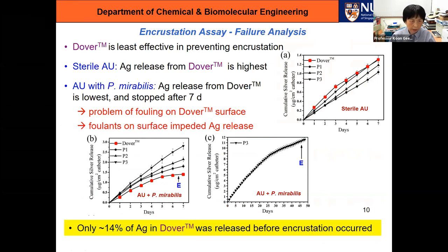So what went wrong with the Dover? This is a commercial catheter. So why is it not effective? Is it because it has limited amount of silver compared to our coating? So what we did is to test for silver release. So this is in sterile artificial urine. So the red squares are the Dover catheter. So you can see the release rate is actually the fastest in the artificial urine that's sterile without any bacterium.